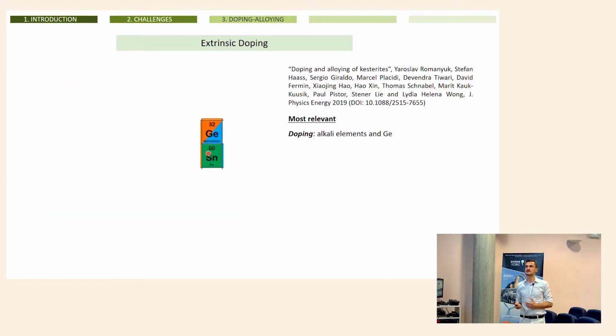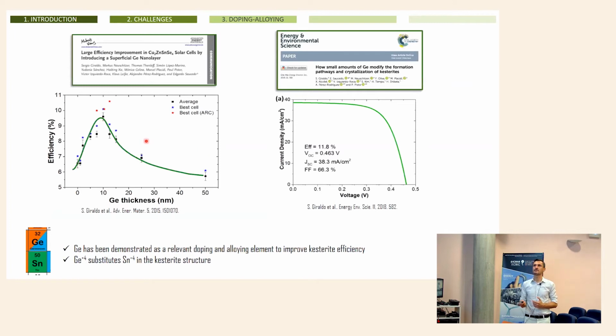The other element that was very relevant for doping was germanium, in the tin position. In that sense, my former group in IREC, we worked a lot and we reported most of the papers regarding this. These are two examples of papers we published on germanium doping, and we observed a large improvement of the efficiency when germanium is included in the system. It's really almost double the efficiency. And some time ago we produced the first record of copper, zinc, tin, selenide in the world by substituting germanium. This was another evidence that tin is the problematic one.